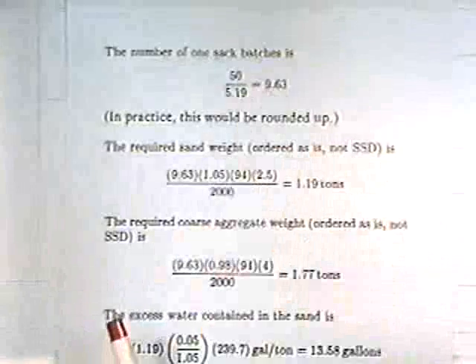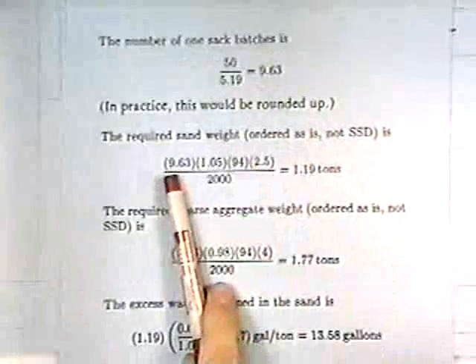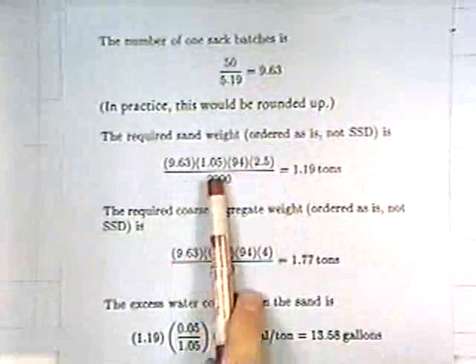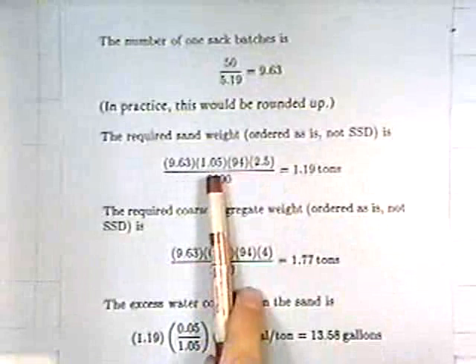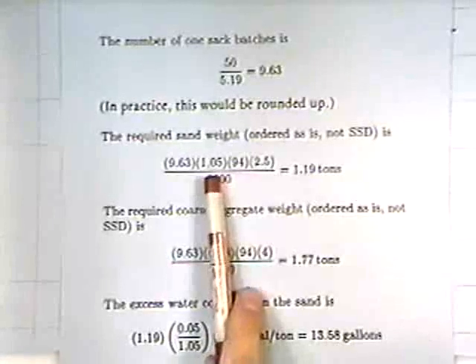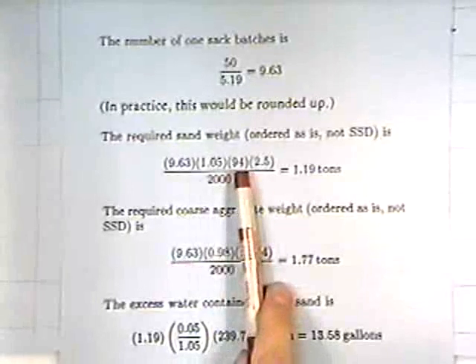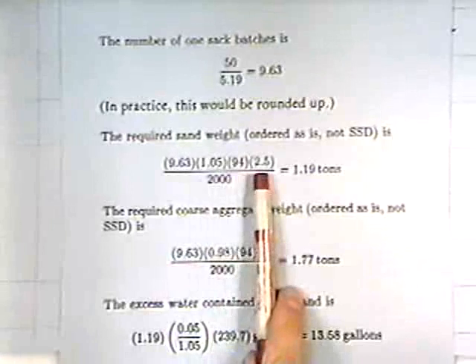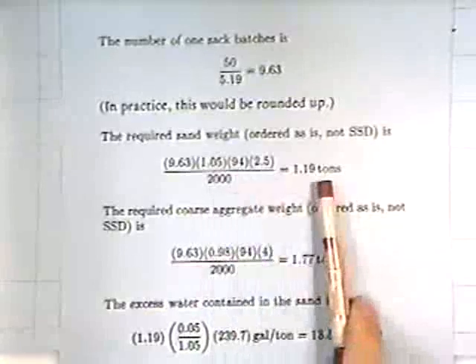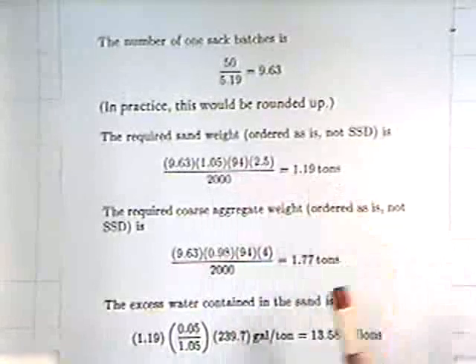Okay? Well, in this problem, they just used the 9.63, but you multiply your 9.63 for finding the required amount of sand. It's the 9.63 times 1.05. Now, the reason the 1.05 comes is because the sand has a 5% excess of water. Okay, so the amount of sand that you're getting is actually a little less. That's why you have to use 1.05 here. Okay, times the 94, which is the weight of the sack, times 2.5 is based on the ratio between cement to sand. Divide by 2,000 to get you into tons. It turns out to be 1.19 tons.